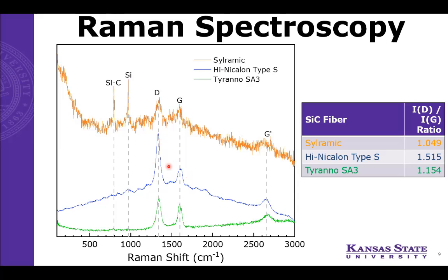I believe, based on literature, this has something to do with the fabrication methods used for this Hi-Nicalon as opposed to the Sylramic and Tyranno, where the Hi-Nicalon uses electron irradiation during fabrication, and one of the properties they've tried to keep in mind when producing those is keeping up the free carbon. We can also see from this graph the similarities between all of these, because it highlights that everybody has a G prime peak, everybody has a G peak, everybody has a D peak. However, Sylramic, despite all of these being silicon carbide fibers, has a higher silicon peak and silicon carbide peak, which is interesting.